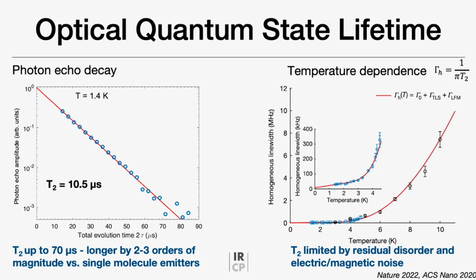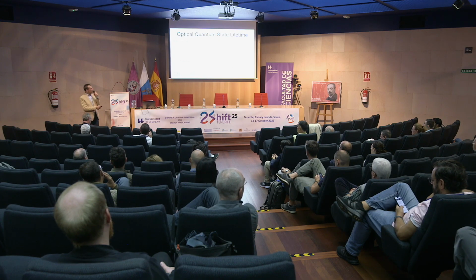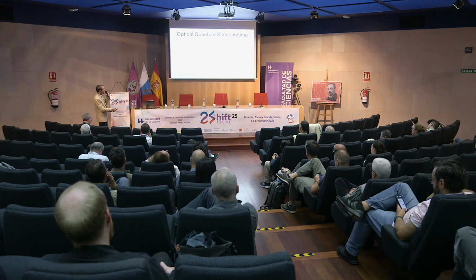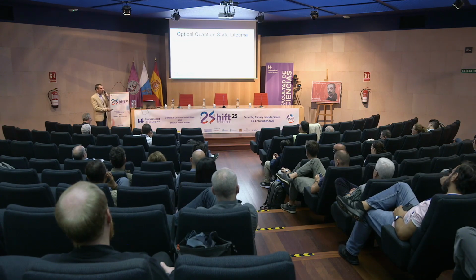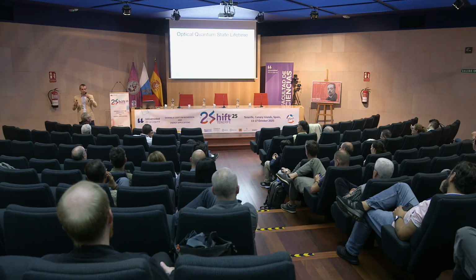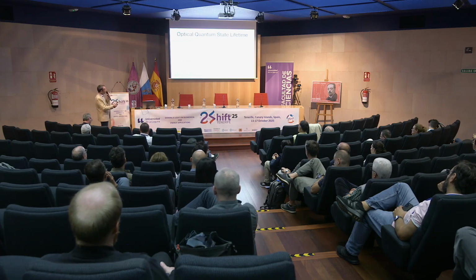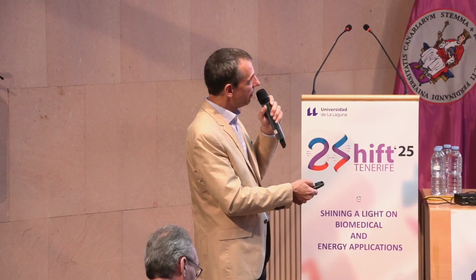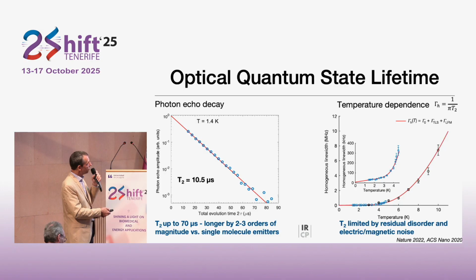One way to look at that is to record the temperature dependence not directly of the quantum state lifetime, but of what is called the homogeneous line width, which is simply inversely proportional to T2. If we plot this homogeneous line width as a function of temperature, we see that when we increase temperature, the homogeneous line width gets broader, which means the quantum state lifetime gets shorter. The different contributions we can identify by a fit to a standard model are first an exponential variation in this region, say above 5 K. But if you zoom on this part, you see a linear dependence at low temperature.